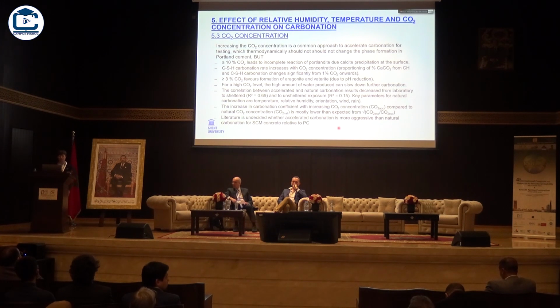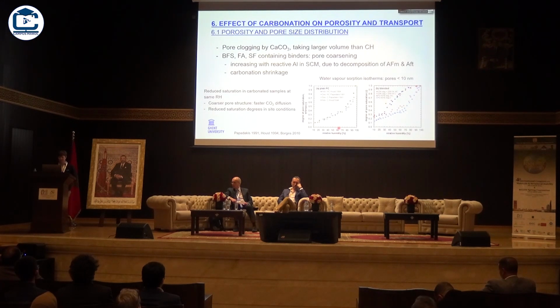Okay, and actually, if you consider the presence of SCM, the literature is still undecided if accelerated carbonation is worse for concrete with SCM than for Portland cement concrete. So opinions are divided there. Maybe something on the effect finally of carbonation on porosity and transport properties.